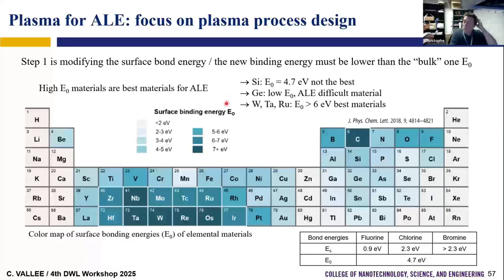So you have to look at the bond energy, and in this table, you have an idea of the binding energy of the different atoms. And you can imagine that for atoms that have very high binding energy, like, for example, tantalum, tungsten, ruthenium, we may have a huge contrast between the surface binding energy and the bulk. So it will be easy to have an ALE window with the energy. But if you have some material like Ge, which has very low binding energy, even if you do chlorination or fluorination, you will not have a huge contrast. So it will be difficult to sputter only one monolayer and not the bulk.